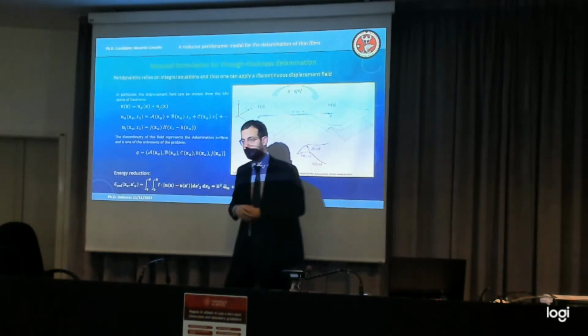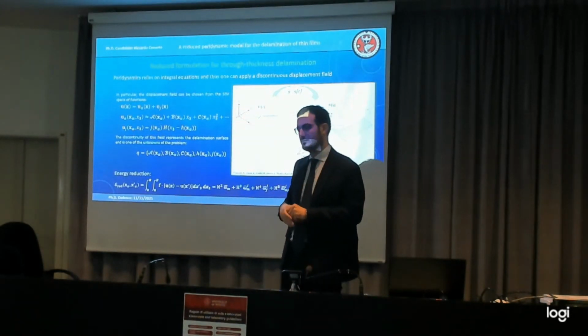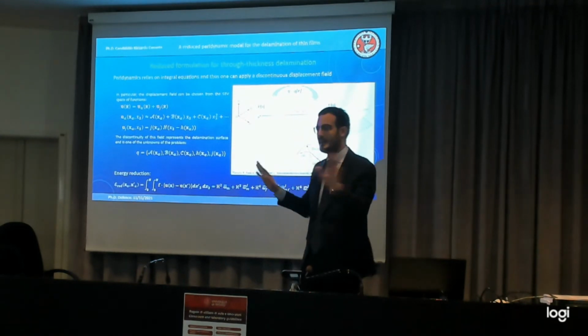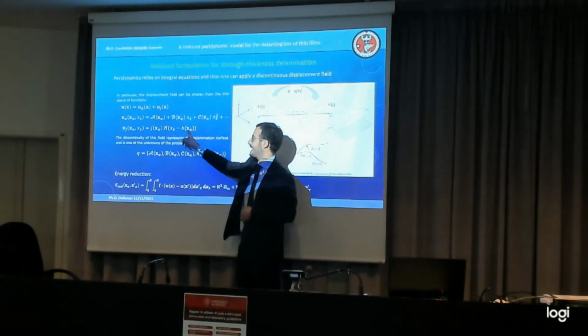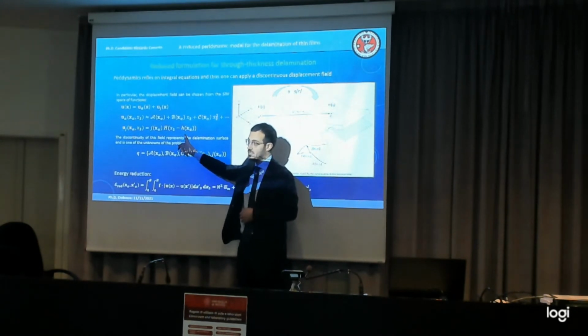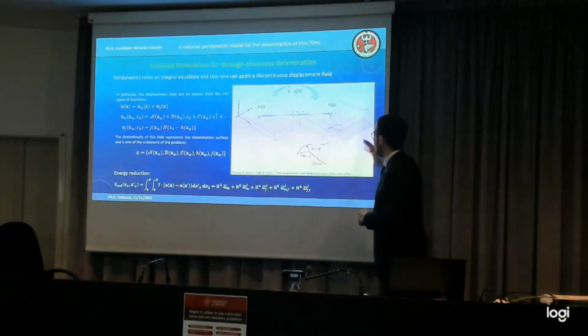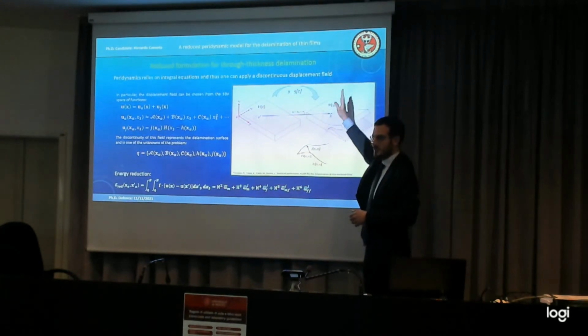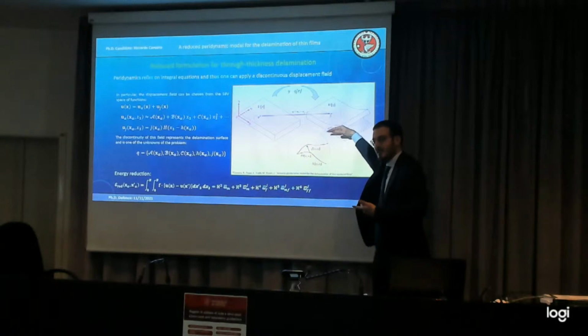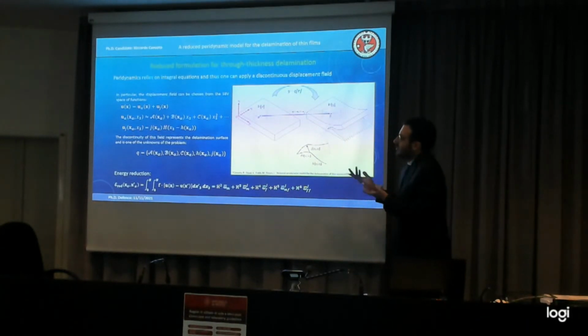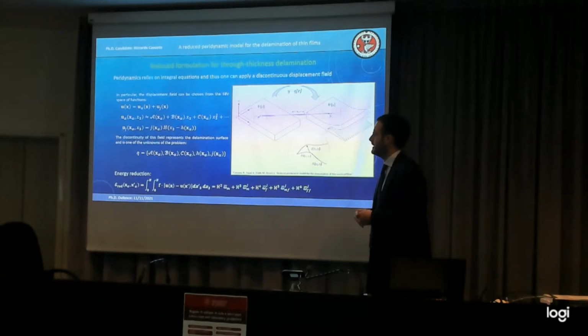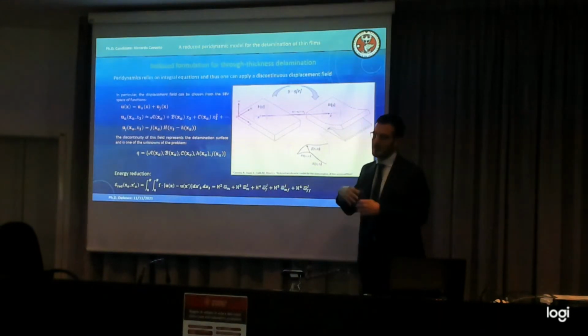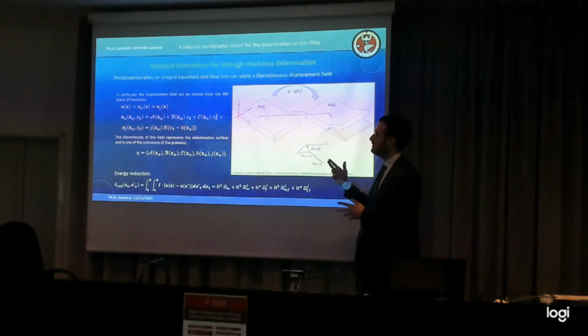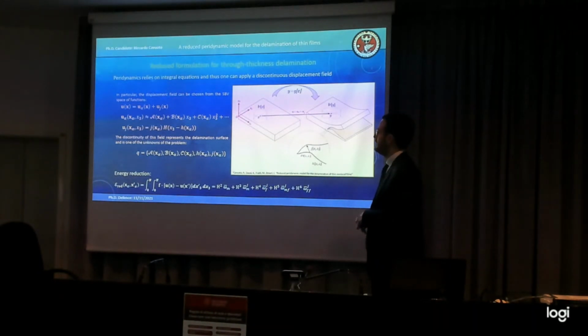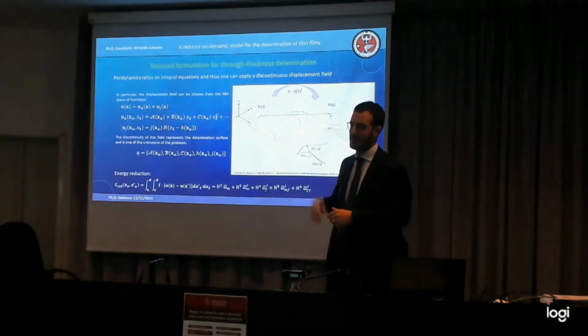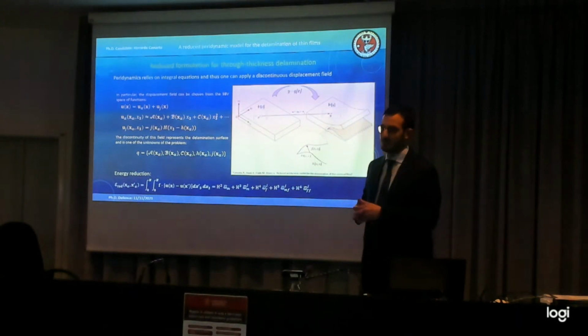With this formulation, you can recover also cracks passing through, not only in the thickness, but you can get every kind of crack, as long as the crack is defined by a function. So you can have something going up as much as possible, or having jumps. The only condition is that it has to be a function. It doesn't need to be differentiable, and it doesn't need to be continuous anyway, because the derivation of the displacement will happen. That is the real strength of the model.